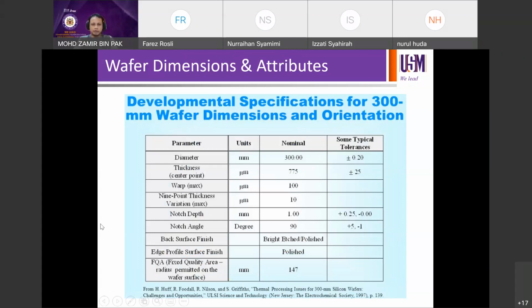So another example of specifications, if you run say 300 mm or 12-inch of diameter. You need to control the diameter of the wafer to be plus minus 0.2 mm. So see the tolerance. Your diameter is 300 mm, and you can only afford a variation of 0.2 plus minus. So you can only go up to 300.2 or 299.8 minimum. So the fluctuation from the supplier, or if you supply the wafers, you can only afford a fluctuation of 0.2 plus minus. Okay, and your center target is 300 mm.